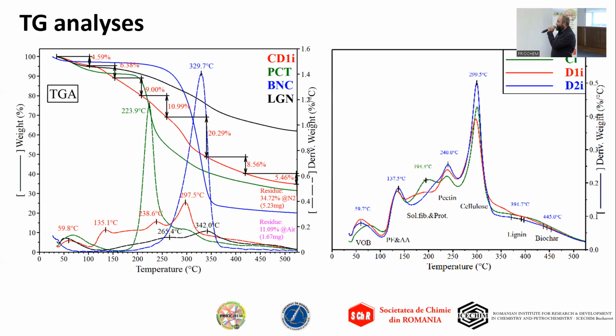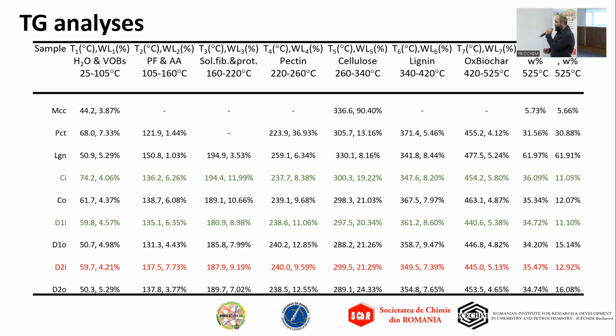We can see through the overlay of these spectra that we have a faster transformation from low molecular compounds into pectin and cellulose for the second dosage. We can also evaluate the weight losses on each thermoregion, and we also see a faster transformation from low molecular weight compounds into pectin and cellulose.